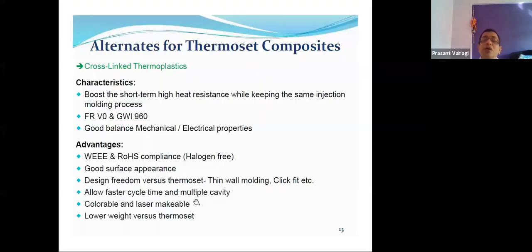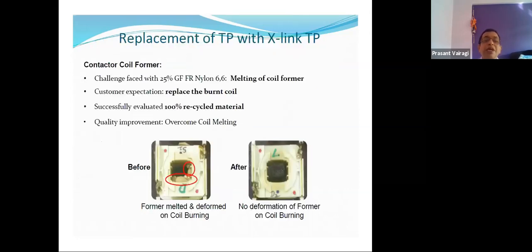After cross-linking, if you carry out the test, you can see that though the coil is burnt, there is no melt deformation. These are the different components that we have gone for with the cross-linkable material. This is the thermoset contactor breach, and you can see the flash, which is the excess material one has to remove. Thermoset material has a chemical reaction taking place inside the mold. Sometimes it sticks to the mold, and the part coming out will show you a short molding kind of feel. So this is another contactor breach, which we have converted from thermoset to radiation cross-linkable thermoplastic material.